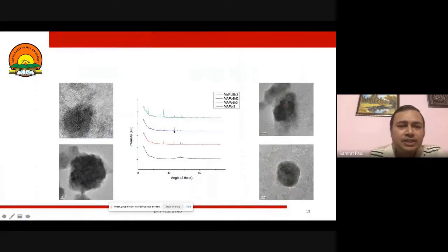Now, after synthesis, we can see that we have covered the perovskite with titanium. Here I have given the perovskites we have made, methylammonium based perovskites. In short, in the scientific community, we call it MAPbIBr2. MA is the organic component, which represents A. Pb is the other, inorganic component, and IBr2 is the X component. So ABX3, with IBr2. Here we have combined 2 halogens to form a special kind of perovskite. And over that we have a core shell structure, a shell of TiO2, which is also mixed phase. So here we'll have 2 PN junctions with 3 materials.